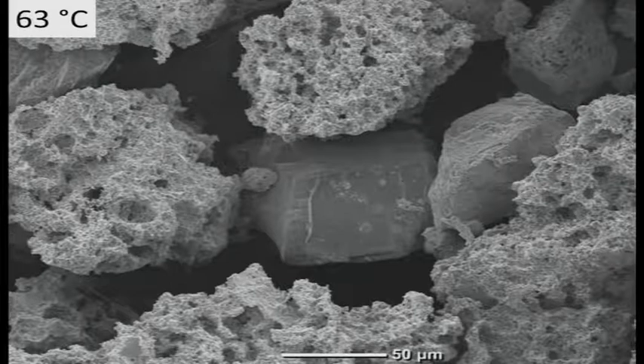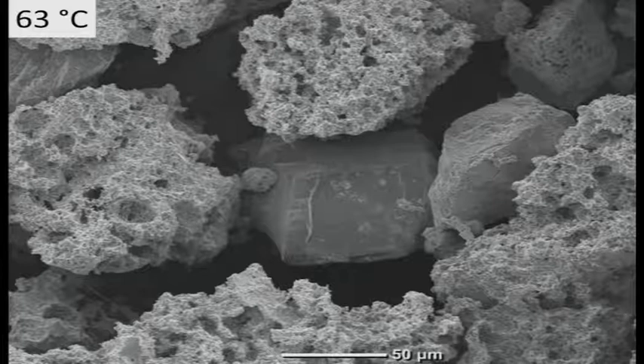And based on the results I've been describing so far, I'm leaning towards the latter explanation, that they formed during the leaching. So when we did spot analyses on these ones, those corroded particles around the outside are near the same sort of elemental ratios as the initial unleached material, which says a few interesting things about the nature of the reaction mechanism. Particles like the ones in the middle are mostly titanium oxides with a few other insoluble things mixed in. I mentioned lead earlier, just sort of there as a radioactive decay product. Lead sulfate is insoluble, so it will not dissolve in sulfuric acid, so that tended to collect in some of these secondary particles as well.